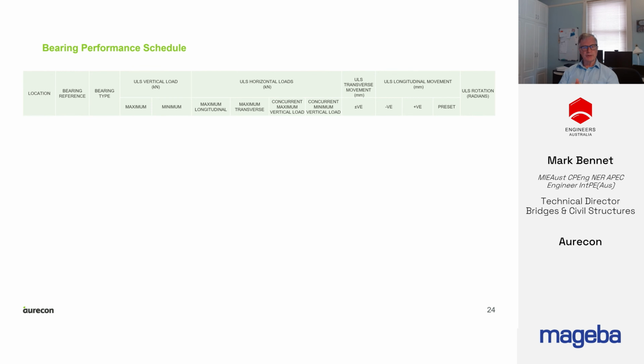A commentary to the latest version of AS 5100.4 is currently being prepared, and a new template for the bearing performance schedule for pot and spherical bearings is being proposed. With this layout, the movement shown on the schedule should include the additional plus or minus 25 millimeters required by clause 2.5. The rotation shown on the schedule is the vector sum of the rotations about the longitudinal and transverse axis of the bridge, increased by an additional 0.01 radians rotation allowance required by clause 7.5. Where the maximum and minimum vertical loads concurrent with horizontal loads are the same as the general maximum and minimum vertical loads, the concurrent vertical loads need not be shown.